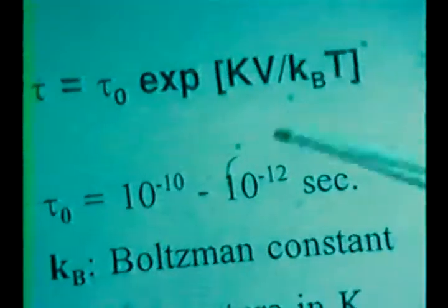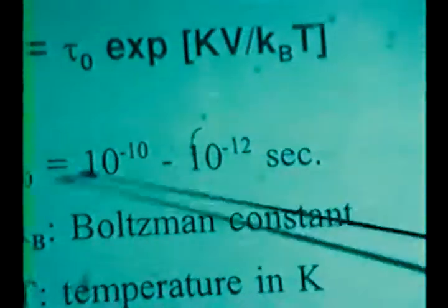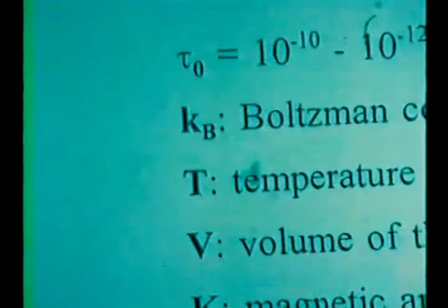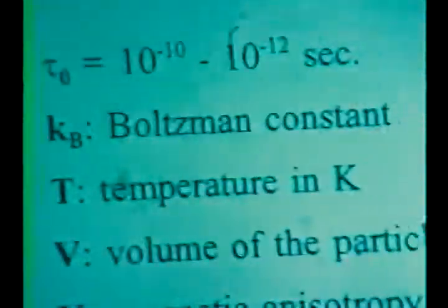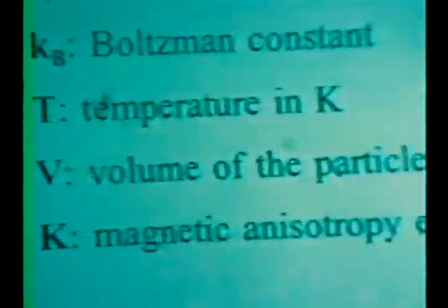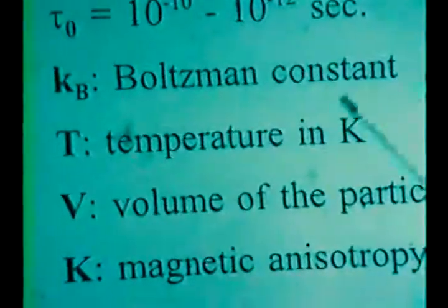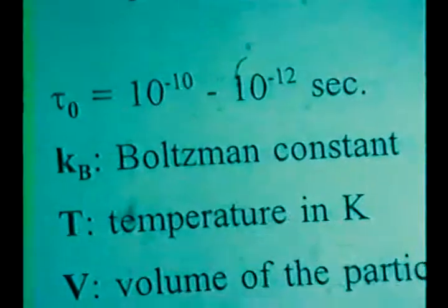The relaxation time is defined as a function of K V divided by K_B T. Here, K is the magnetic anisotropic energy, and it depends on the shape of the particle, the stress of the particle, and the surface of the particle. V is the volume, and T is the temperature. Tau 0 and K_B are constants.